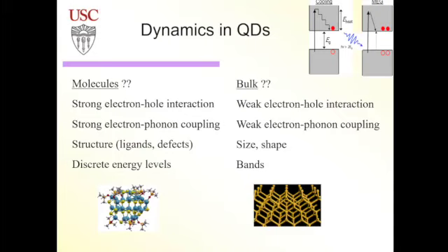One idea was to design materials in which you use the extra energy to excite a second electron hole pair. So one photon should give you two excitations, two electron hole pairs, which is not easy to achieve. This is how we came into this field in 2005 or so. Then we started to think: if you compare molecules versus inorganic bulk semiconductors, you realize that properties are quite different. In a molecule, you can shine light on the molecule in your eye, that's how you see, the molecule isomerizes, you break a double bond. So there's very strong electron vibrational interaction. But if you shine light on a bulk semiconductor, probably nothing is going to happen.